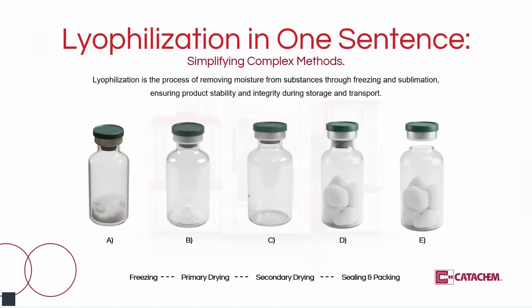In one sentence, lyophilization is: freeze the product, reduce pressure, sublimate ice during primary drying, then desorb bound water during secondary drying, all while staying below critical product temperatures. Lastly, seal the container to preserve what you've achieved. This sentence sounds simple. The complexity is that every variable interacts: formulation, fill volume, container geometry, shelf mapping, freezing rate, chamber pressure, ramp rates, and the endpoint definition for moisture. If you change one, you often change 2 or 3 others, with the results as varied as those shown in the vials that are illustrated.